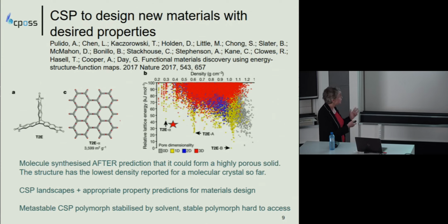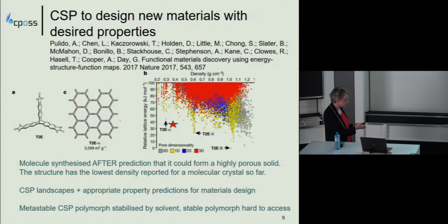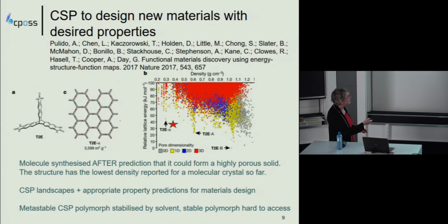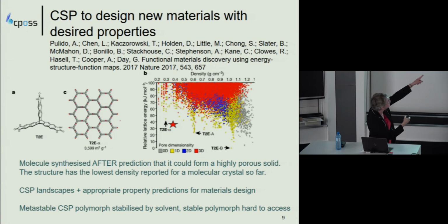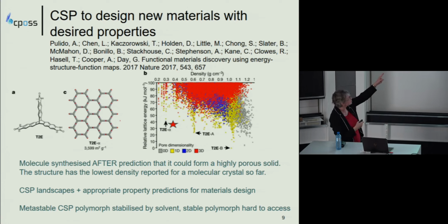The structure was found. It had the lowest density reported so far from a molecular crystal. And here you see every structure they've generated is classified by the dimensionality of the pore for containing the gas molecules. And the one they've got here, naturally found, my pointer isn't working, T2E-A, where the star is, highly metastable. That's the structure there looking down the pores.